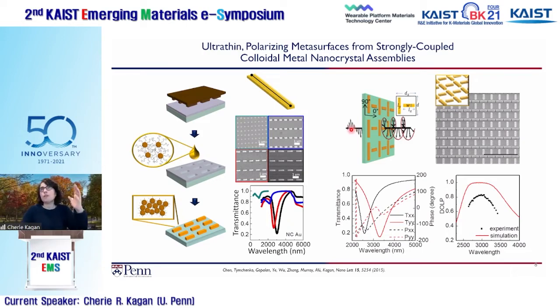And so we used a linear polarizer to analyze how linearly polarized the transmitted light was. We measure something called the degree of linear polarization. It's basically just measuring how well we did at converting circularly polarized light into linearly polarized light. We can see in experiment, we had about 80% success in converting to linearly polarized light. And the red structure here is showing what it would look like in simulation. Of course, our fabricated structures aren't always quite so perfect. These two are getting a little closer together.